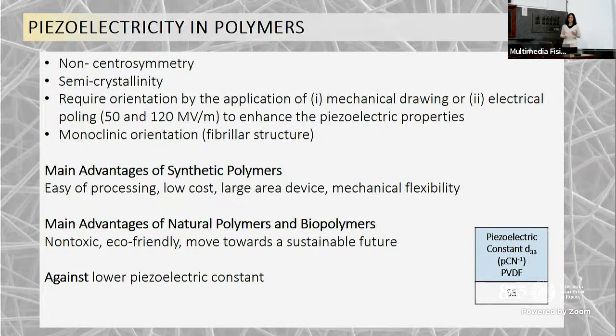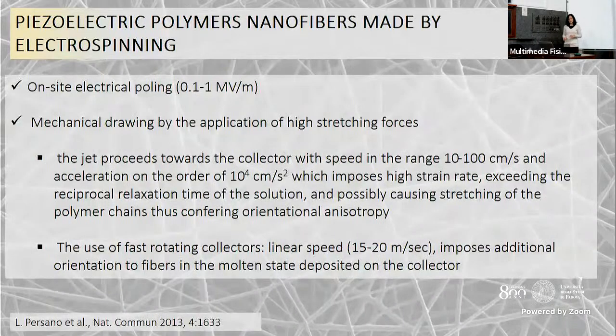What are the main advantages of synthetic polymers with respect to inorganic materials? Of course, the ease of processing, the low cost, the capability to make large area devices, and their intrinsic flexibility. Additional advantages come from the use of natural polymers, which are non-toxic, eco-friendly, and they also will help us toward a more sustainable future. There is one drawback, which is the piezoelectric constant, which is lower with respect to inorganics, and in particular with respect to lead-based inorganic materials. So, what are the advantages of using electrospinning to make nanofibers, and in particular to make piezoelectric nanofibers?